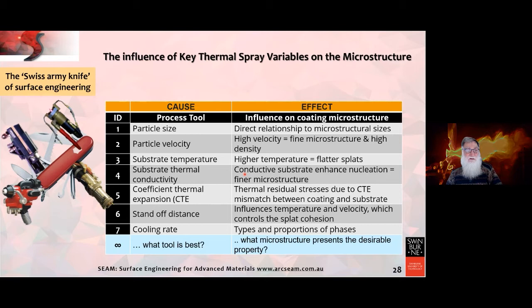So first of all, we have our Swiss Army knife, and now we've got all of these torches, and these torches give us different temperatures and velocities and spray patterns. So we have a cause here, it's the process tool, and then the effect on the coating microstructure. So we have number one, the particle size, that's related to the microstructural sizes of the coating, the velocity, the temperature, the conductivity, the expansion coefficient, standoff distance, cooling rate. So I have many tools as shown in the previous slide, and all of these impact the microstructure.